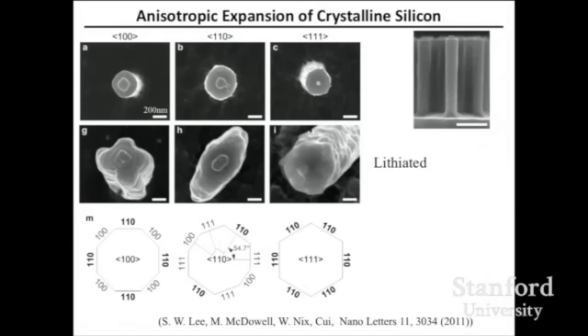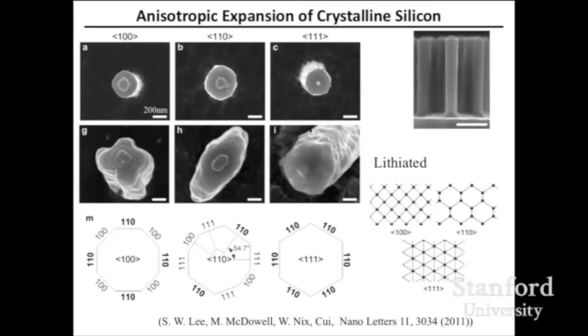And it turned out this expansion all happens along the 110 direction. This has four, so it has four directions. This has two right here, the sidewall. And 110 is quite unique. 110 has this crystal structure with open channels, ready to react with lithium. It goes very fast.